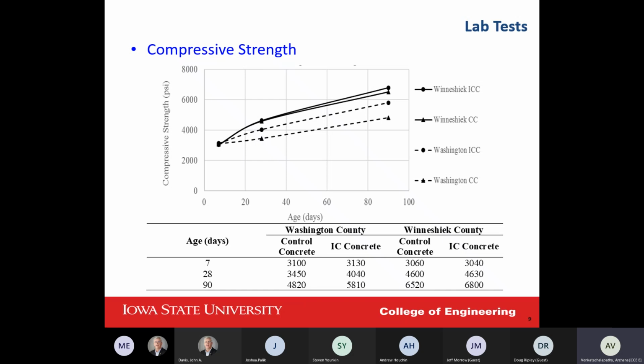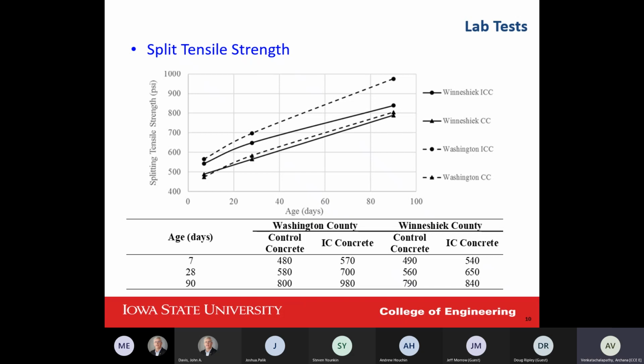So we can see in both construction sites, more or less after 20 days, 28 days, the concrete compressive strength is showing higher strength, after, I don't know, 86 days, for about 10%. And yeah, that means the hydration is showing the result. And also that increases the split tensile strength more than we expected, because in Washington County, as we can see, that was 800 psi for the normal concrete, but that raised up to 1,000 psi for the internal curing method.